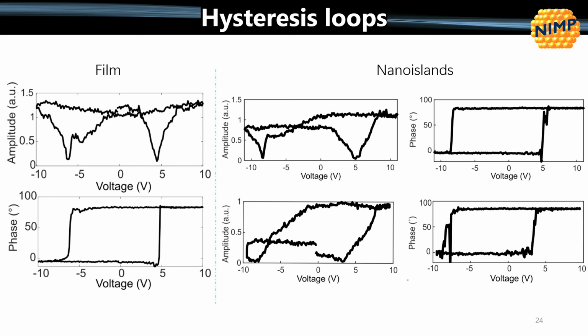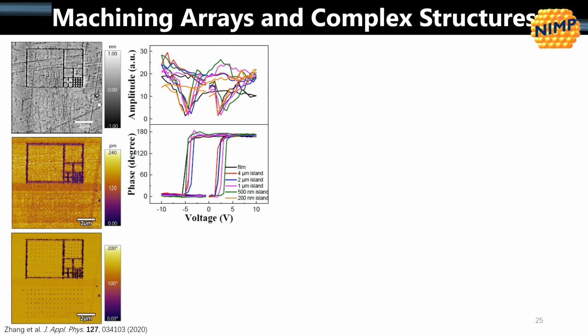Comparing, again, the film with a couple of different nano islands, it's not a statistical approach, it's a couple of examples, but we've lost that symmetry a little bit, and it looks like the coercive field has changed, maybe even some more imprint. So it's something to keep an eye on in terms of understanding what the limitations are.